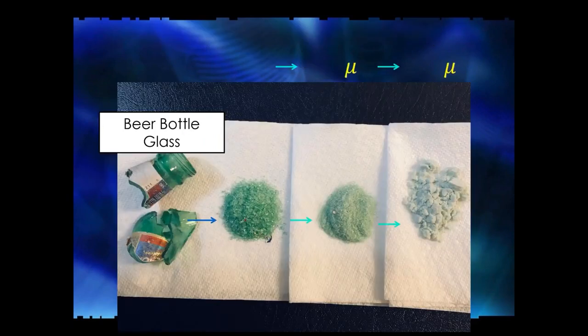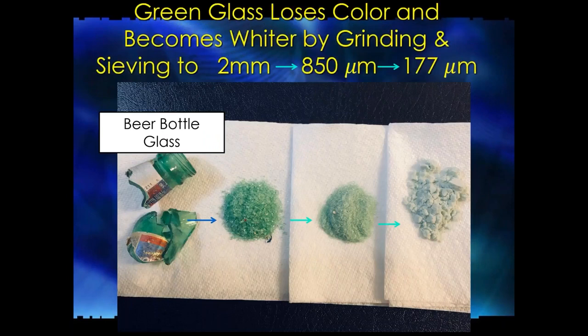So what is a cheap way to make a pigment? Well, if you take a beer bottle and grind it to 2mm, then to 850 microns, then to 177 microns, and keep grinding this down, as you get it down to a quarter micron, it will be just unbelievably white. And so you look at that and say, well, why don't we just make paint out of ground beer glass? And the answer to that is that as the resin fills the voids where the light is in between the particles, you go backwards and backwards, and eventually you reveal the true nature of what that particle is in a matrix.